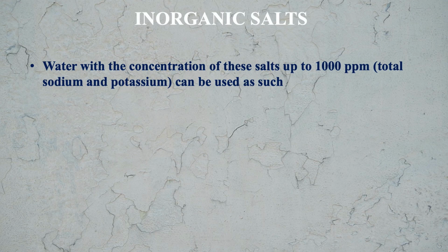Water with concentration of these salts up to 1000 ppm, meaning combined sodium and potassium, can be used as such. Means no other intervention is needed. You can use such water which has a total sodium and potassium concentration up to 1000 ppm as such.